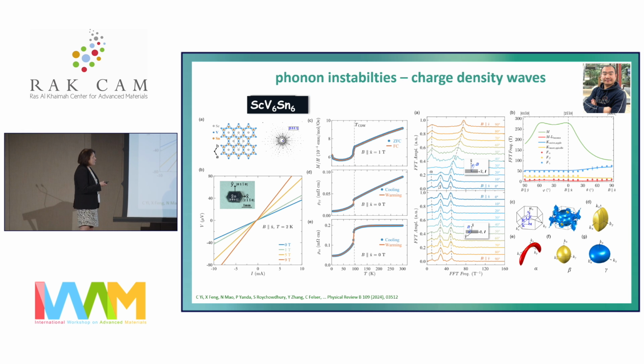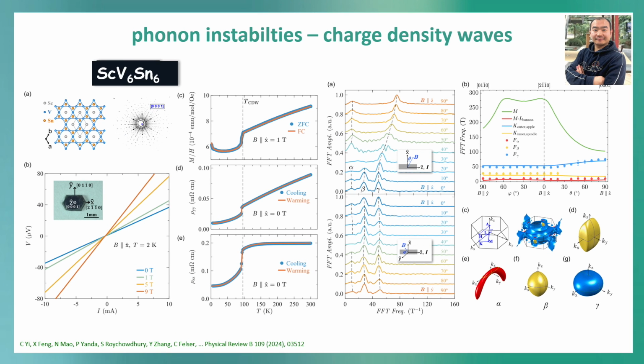The other thing is, many of them, if you look more carefully, you see they really show strange behavior in the transport properties, like here in the resistance, for example, there are jumps. And they show nice quantum oscillations, so we can make very nice single crystals. I'm really amazed that we can even grow single crystals of ultra high quality in magnetic compounds. This is not a magnetic compound, but still. Where you have very nice quantum oscillations, you get the whole band structure from the measurement, and you can really revisit all these compounds, and you see even some interesting transition, and indeed what we have expected for a system which has a Van Hove singularity.